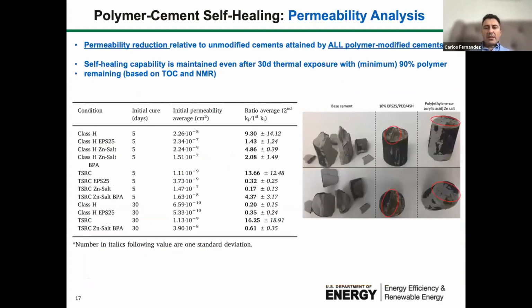So this is permeability. We did also compressive strength. I measured that in the previous talk, but you can see here what I just mentioned in the previous slide. The control cement, particularly cement H, when you generate a fracture using a modification of the Brazilian test, where you put two loads, one higher than the other, and you displace this and generate a shear fracture. In the case of control cement, because of brittleness, you end up in some cases with material that looks like this picture.